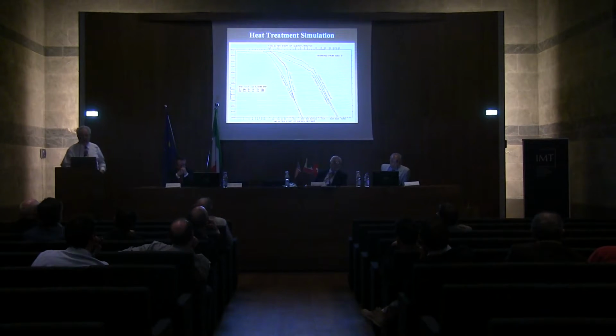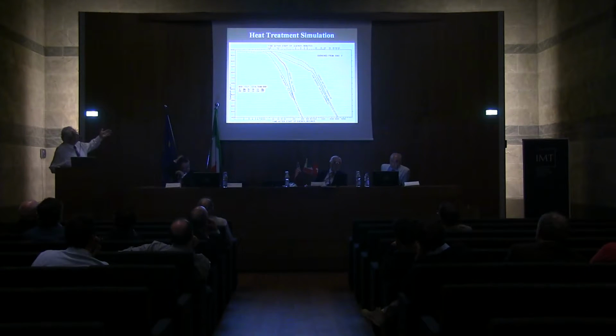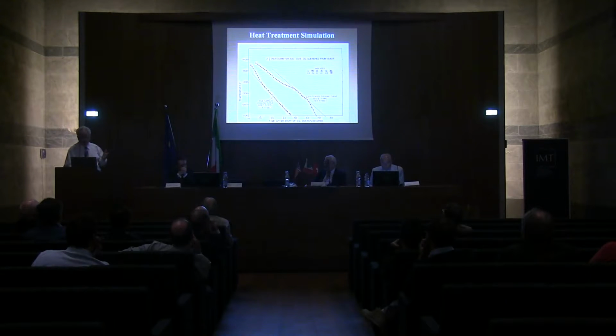So we were trying to not only determine that it was oil quenched, but also that it was not air-cooled. Now, here are examples of the data that I got by using 1025 carbon steel, which is the closest thing I could find in the research center that was the right diameter. And we put thermocouples in subsurface and center locations. And we're quenching this from 1580 Fahrenheit, as the eye bolt was supposed to be austenitized at. And you can see the cooling rates here for the oil quench are much faster than the cooling rates for air cooling. So that data is very useful.